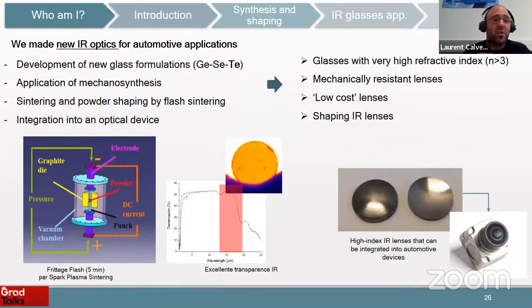So at the end of the project, we developed some new infrared optics for automotive application. We developed some glasses with new elements like tellurium, and we used mechanical milling and SPS, as I showed you before. So at the end, we obtain glasses with very high refractive index. They are mechanically resistant, low cost, and as you can see here, we shaped some lenses, and here is the device we obtained on automotive that is now placed on some pretty expensive cars, but it works. And so the cars are close to driving by themselves during the night.